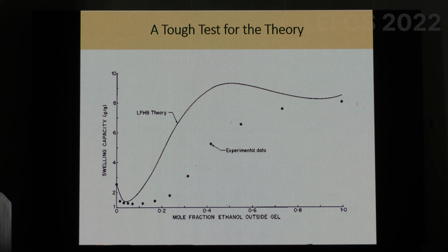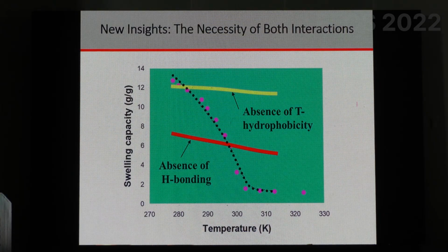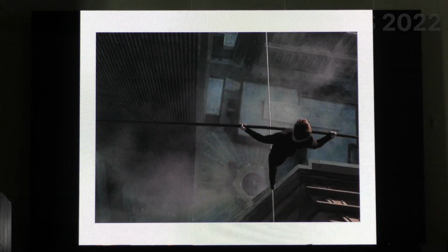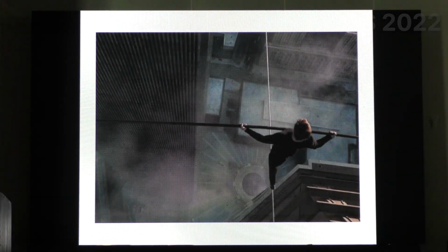So we were now very sure that this model really works well, and said, what else can we do with this theory? And the first thing we realized is that if I cut off the hydrophilic interactions, the gel does not undergo volume phase transition. And if I do the same with hydrophobic interaction, the gel again does not do volume phase transitions. So the presence of these two is very critical. And if you remove one of them, then the volume phase transition goes away. And that's why I said the trapeze artistry, the subtle balance between hydrophobic and hydrophilic interactions is very, very critical to these kinds of volume phase transitions. And that's why I said, you have to have this beautiful balance. Otherwise you'll fall off.